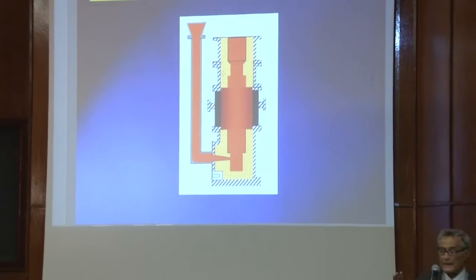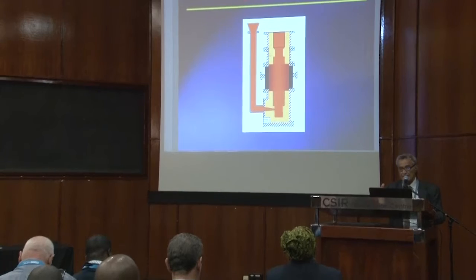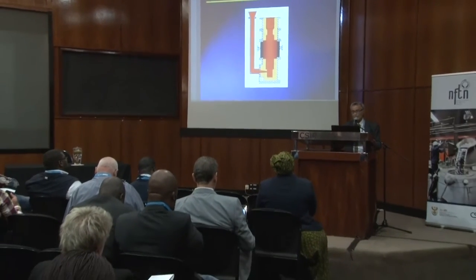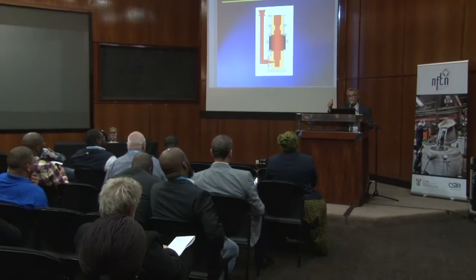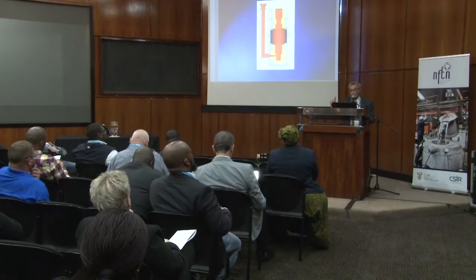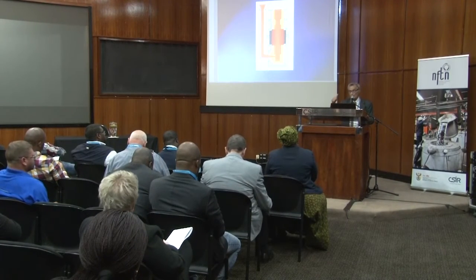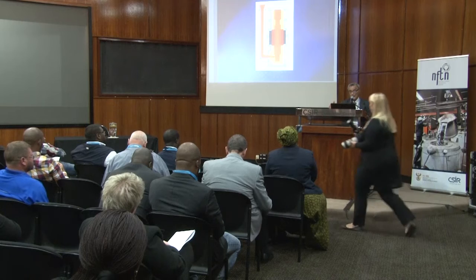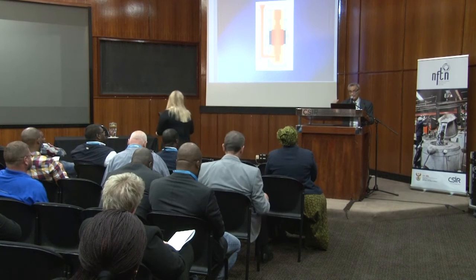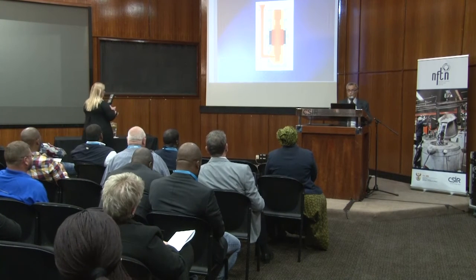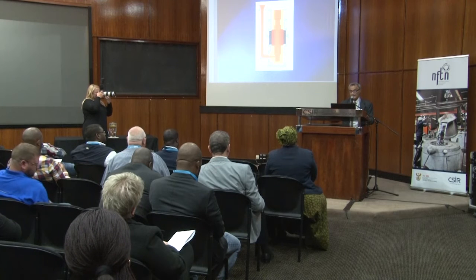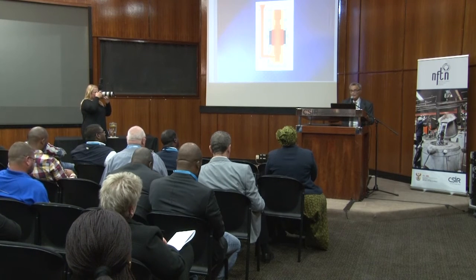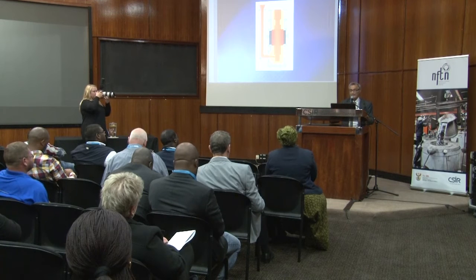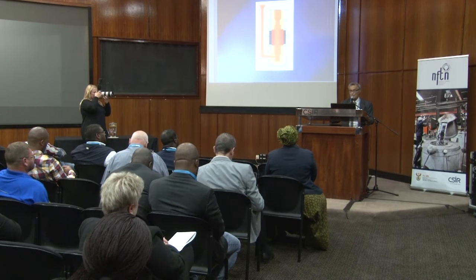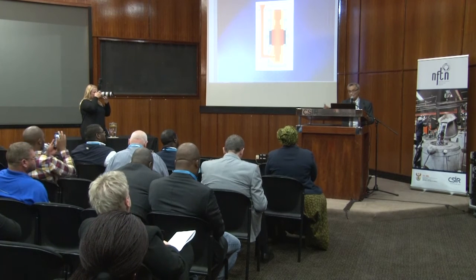This is possible, but if you need high hardness at the roll surface, you have to increase the carbon content to form carbides, and add some chromium and some nickel: chromium to form chromium carbides with the carbon, and nickel to enhance the formation of martensite on the surface for higher hardness. If you increase carbon, chromium, and nickel, you will be fine with the barrel, but you will increase the hardness of the necks. And then there's a danger that the necks will be broken during operation, which may lead to catastrophic accidents, really.